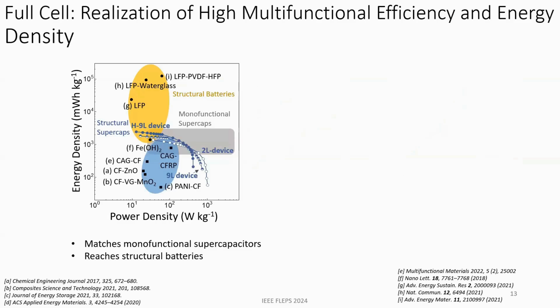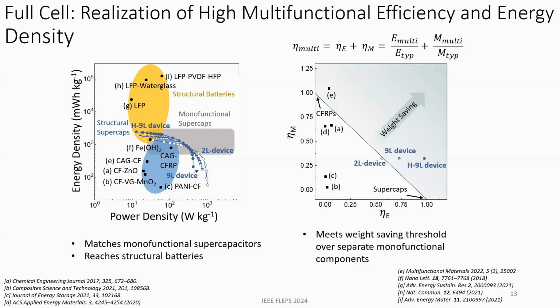And then finally, we can look at our performance against prior works by looking at our Ragone plot and multifunctional efficiency. So here's the power and energy comparisons, and this blue area is structural supercapacitors. The gray is monofunctional supercapacitors, and the yellow is structural batteries. So for our 2-layer, 9-layer, and a 9-layer device with the higher active material loading, they all outperform prior structural supercapacitors, and these middle regions reach monofunctional supercapacitors. And then for the 9-layer devices, they're actually able to reach the structural batteries, outperforming this iron oxide battery.